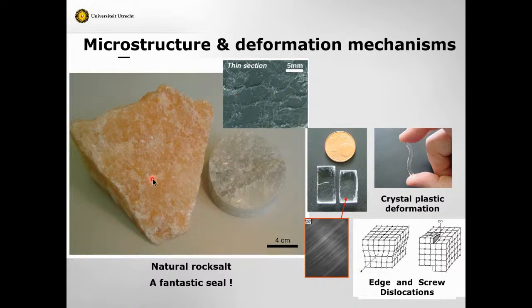And the most striking thing about this material is that the individual grains can deform by crystal plastic processes. Here you see some single crystals of salt that have been deformed in the lab, unconfined, by students in Utrecht, and you see dislocations, slip lines on the surface. So crystal plastic deformation occurs within the crystalline grains by motion of dislocations, edge and screw dislocations. Here's a lovely example. This is me, maybe 15 years ago, actually squeezing and bending a single crystal of salt between my fingers. You can do it if you know how. Questions can be answered later. Okay, it's a wonderful demonstration. You can do it with your bare hands, even me.